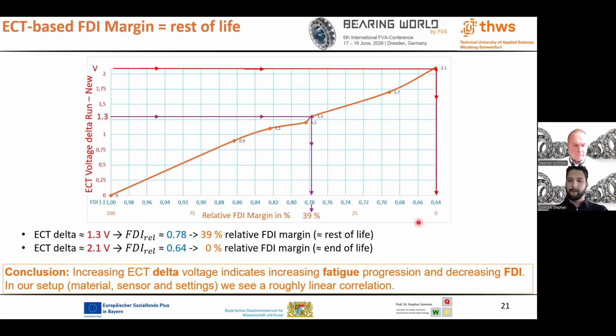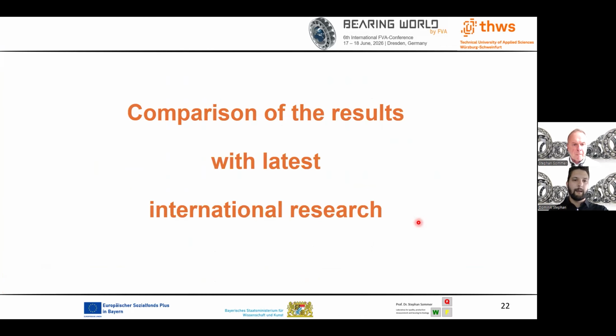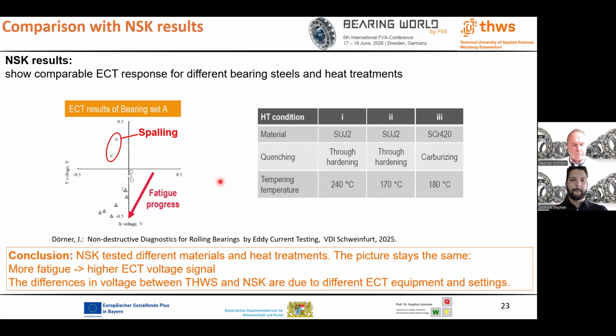The important conclusion is that increasing ECT delta voltage indicates increasing fatigue progress and decreasing FDI. In our setup, with this material, sensor, and measurement settings, we see a roughly linear correlation. After presenting our own results, the next slide compares the trend with recent international research.